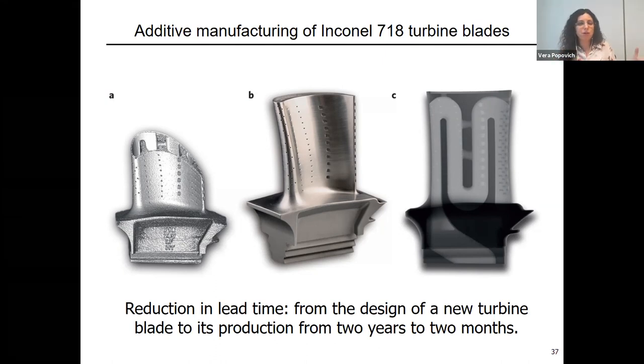Additive manufacturing is actually not new, that goes back to the 60s, 70s. It's just in the past 10-15 years that it picked up again with the development of hardware and software, and more demands from our engineering applications for sure. With additive manufacturing, the laser beam or electron beam is directed on the metal powder, so it's a layer by layer technique. It's heated and melted together based on a CAD model. Then the laser is removed and the metal cools.